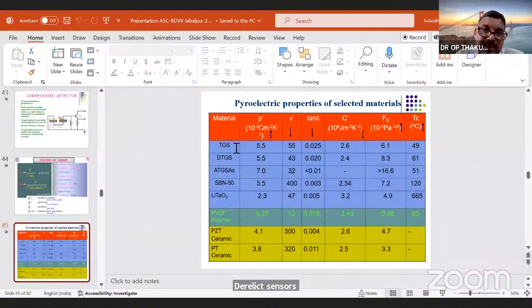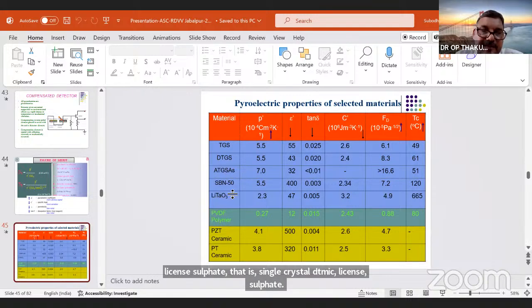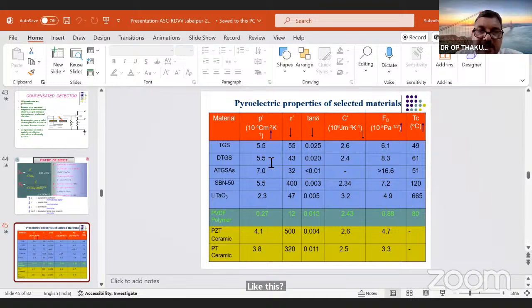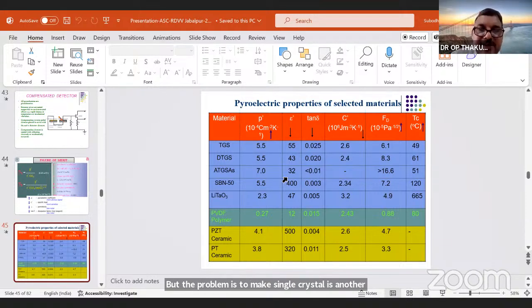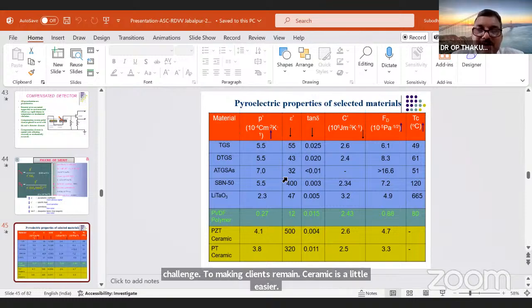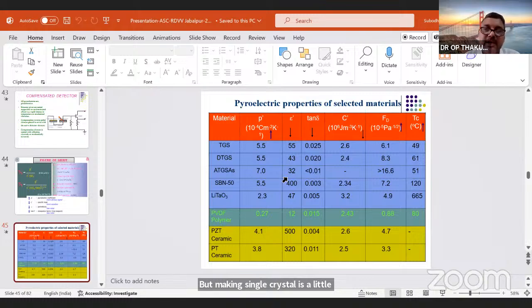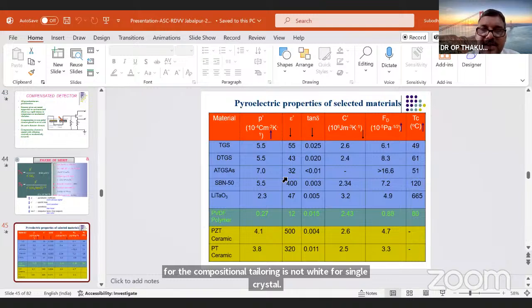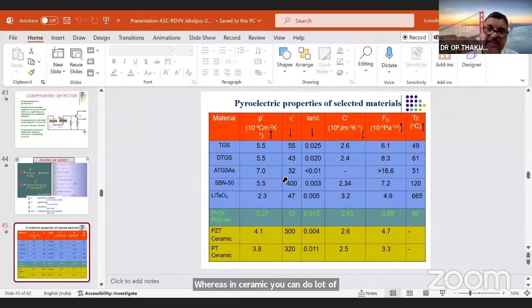So this blue shaded portion, TGS, triglycine sulfate, that is single crystal, DTGS, deuterium triglycine sulfate, SBN, strontium barium niobate, lithium tantalate. All these materials belong to the single crystal family. They are giving good response, but the problem is that making single crystal is another challenge. Making polycrystalline ceramic is a little easier, but making single crystal is a challenging task. And the compositional tailoring is not wide for single crystal, whereas in ceramic, you can do a lot of variation either by changing the composition or by changing the processing parameters.